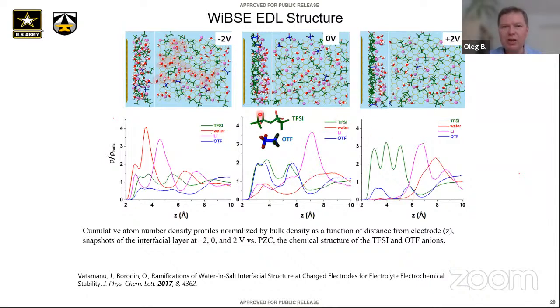That happens because TFSI has two oxygens which can be oriented towards the graphite, and the other two, it's a high concentration electrolyte, so they have to coordinate lithium, right? It's a very high lithium concentration, very little water. You have to rely on anions to both screen the charge and coordinate lithium. However, in triflate, if you have lithium next to oxygens, and that's actually the case, which I'm not going to be showing, then triflate doesn't screen the electrode charge as well, right? So you have to choose either to coordinate or not screen the charge well. That's why, if there is no charge, triflate is present equally, or proportionally, I should say. While when there is charge, the CF3 group doesn't screen the charge. It still wants to be coordinated to the lithium, so it gets pushed out also.